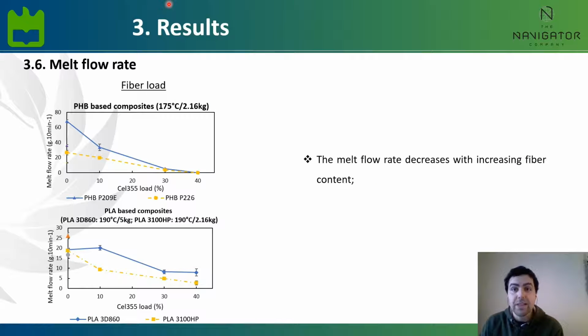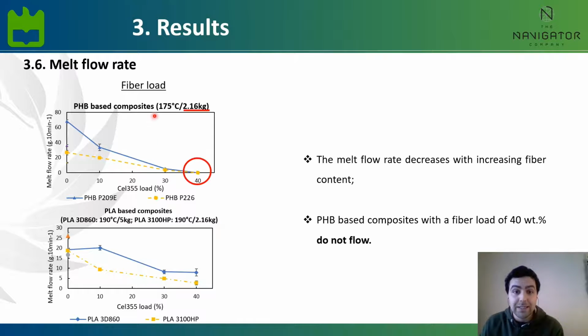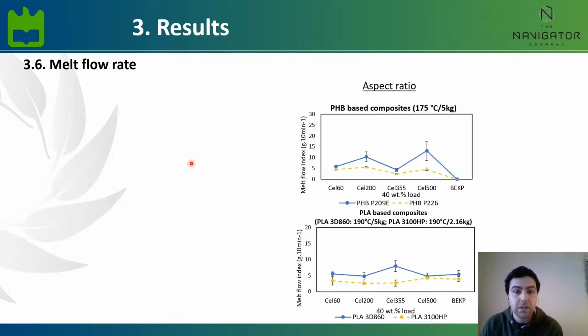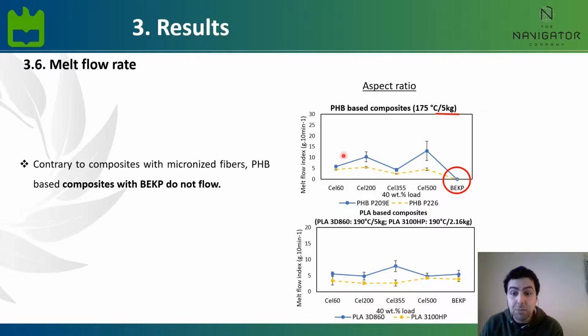To conclude the results section, the melt flow rate assays show us that, regardless of the matrix, the increase in fiber load leads to a decrease in the melt flowability of the composites. Moreover, in these specific conditions, the PHB-based composites with a fiber load of 40% do not flow at all. However, when applying a different weight, all the PHB-based composites with micronized fibers flow, but composites with non-treated bleach eucalyptus kraft pulp do not flow. And that may be a consequence of the fiber shortening upon the mechanical treatments that may lead to a higher mobility of the fibers within the composite in molten state. As for the composites with PLA, regardless of the use of fibers having different aspect ratios, or even the use of bleach eucalyptus kraft pulp, the melt flow rate remains more or less unchanged.